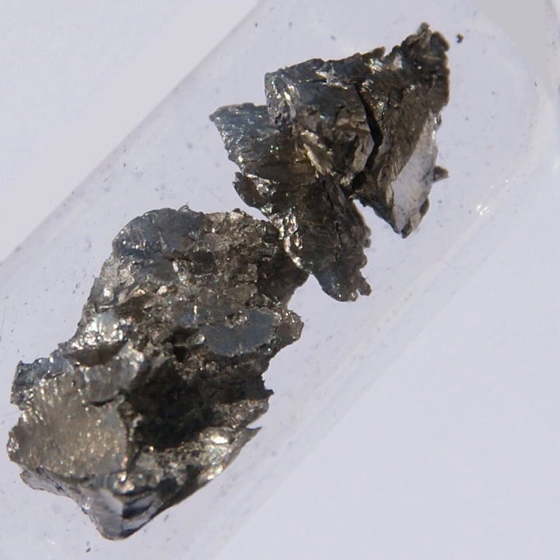The oxalates are converted to oxides by annealing, and the oxides are dissolved in nitric acid. This last step excludes one of the main components, cerium, whose oxide is insoluble in HNO3. Care must be taken when handling some of the residues as they contain 228Ra, the daughter of 232Th, which is a strong gamma emitter.